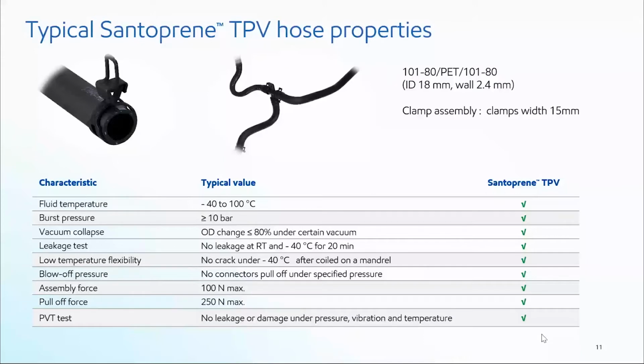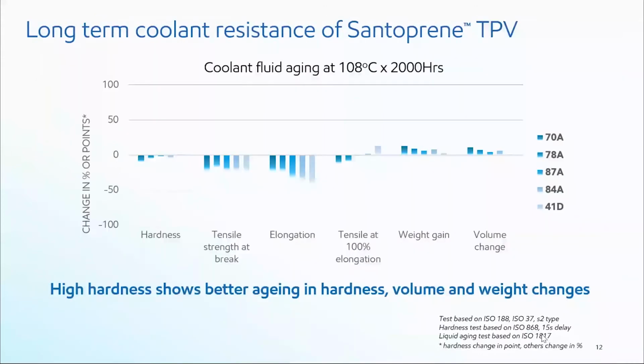Okay, now I will talk specifically about the long-term coolant resistance of Santoprene TPV, because at the end of the day, the hose needs to convey the coolant and the material used should be resistant to the coolant that is used. So we have aged Santoprene in this coolant at 108 degrees C for 2000 hours. It is a pretty long duration.